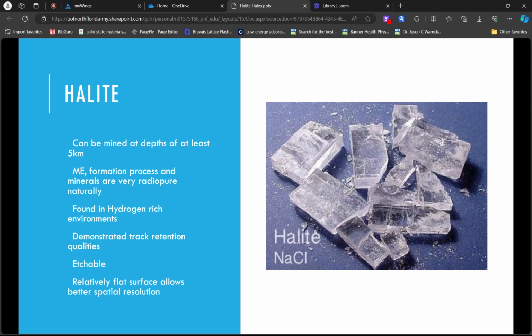Another thing about it is that it is etchable, and we have defined a pretty solid etching rate. The fact that it's etchable helps tremendously because we can take those really small nanoscale, half a nanometer, angstrom-size interactions and blow them up to 100 times bigger, even more than that, with some plasma, which is our strategy. We'll get into that later. We preferentially etch those little defects caused by those interactions into larger, more optically observable information that we can then transform back to the original energy and get back the information we want.